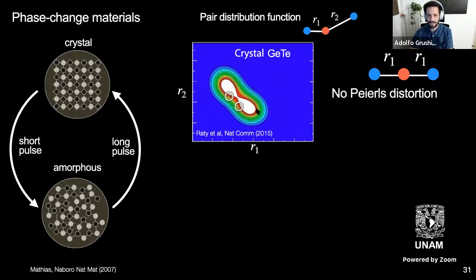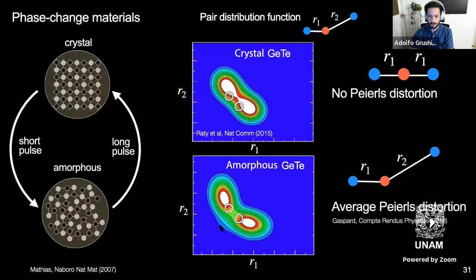I mean, ideally, if this was perfectly equal R1 and R2, then you would find just a central blob. But here you find a little bit skewed. But nonetheless, essentially, compared to the amorphous, which I'll show next, there's no what we call Peierls distortion, meaning it's equally likely to find the blue and the red at the distance similar to the red and blue. However, in the amorphous germanium tellurium, what happens is that it actually splits into two maxima.